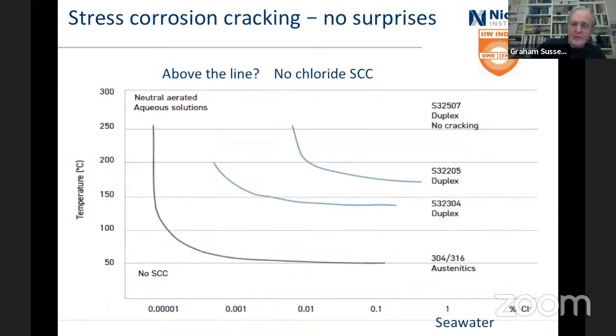Stress corrosion cracking. This is Sandvik data, where we're looking at the 304 and 316, which really won't cope with very much in the way of chlorides. 50 degrees C and a few parts per million, and you can get cracking. Duplex distinctly more. We're up at what, 140 degrees, and super duplex is up even more. And these are regularly used at quite high temperatures and get no cracking in seawater. And just from the point of view, that's seawater there.